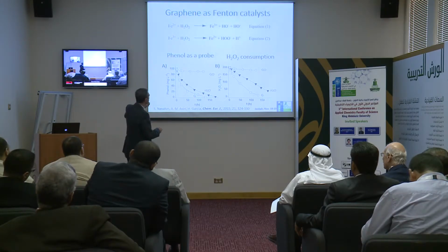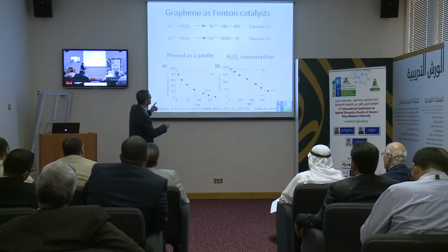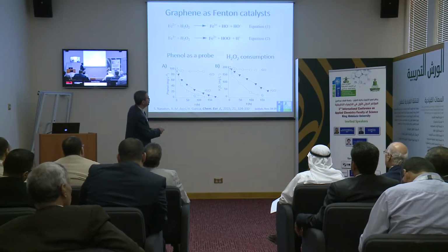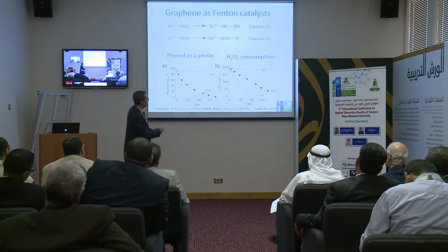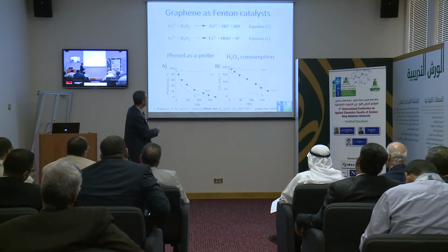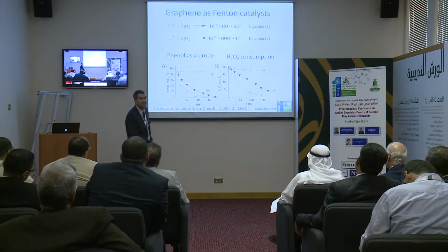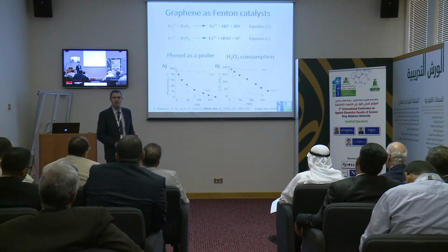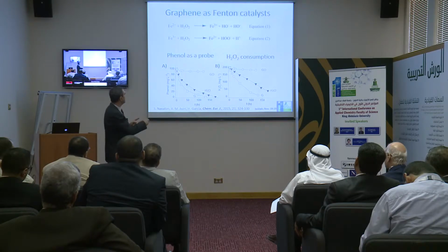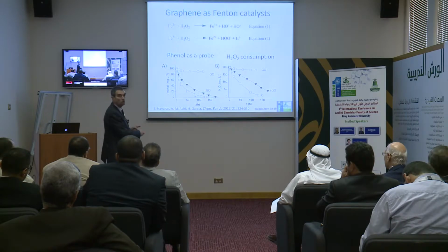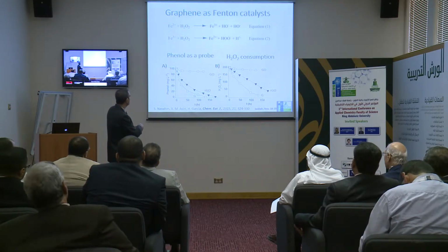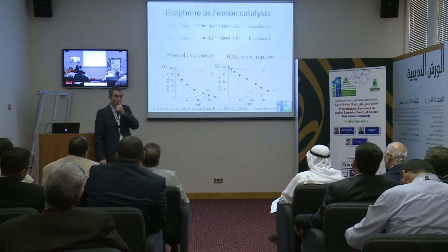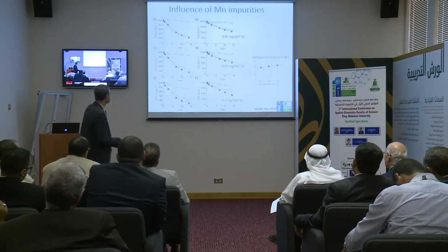But one thing that is important is to compare this phenol with hydrogen peroxide consumption, and then you measure the slope of this plot and the slope of this plot, and you have to find that they are parallel. This is very important because this means that hydrogen peroxide is only decomposed making this reaction. It is only decomposed making the Fenton. If you degrade one phenol, then you have to decompose two molecules of hydrogen peroxide. Actually, when you compare this scale and this scale, you will observe that we have the double.